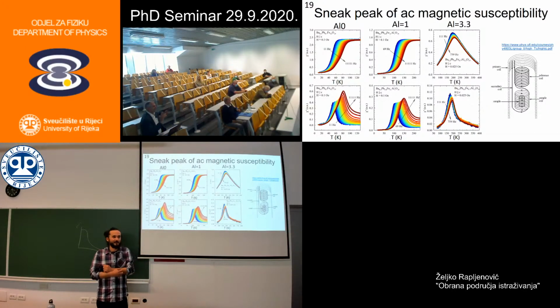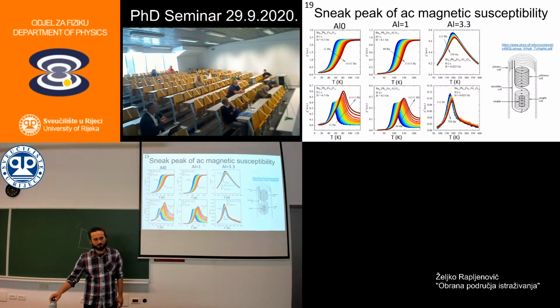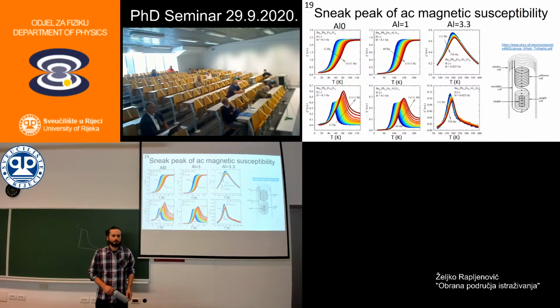I'm just saying, whenever your technique is surface sensitive, you have to take care about conclusions, because the surface can affect your measurements very much. Just look at the silicon surface. It's well known, and a Nobel Prize was won on STM of the 7x7 reconstruction. It's a huge unit cell, so semiconductors are known to make very strong reconstructions on the surface.